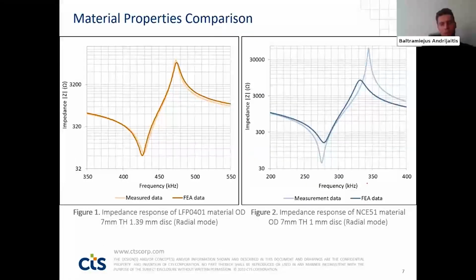Now that we are familiar with the properties of the lead-free LFP0401 material and compared it to lead-based material, let's take the exploration one step further. So here is a comparison of the previously introduced materials in the shape of a disc, 7 millimeters OD, outer diameter, and the finite element model is presented. Simulations were performed with Onscale software. On the left, we see quite good matching of the curves of lead-free samples. There, the material matrix was tuned accordingly to measured data, cooperating with the Onscale team.